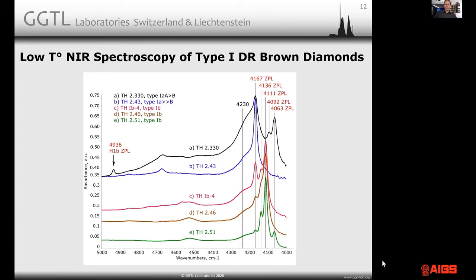So this is the low temperature work we've done on the Amber Center. You can see here on the left in the trace A, there is H1B zero phonon line. That might be surprising for many, that you find H1B in just a brown diamond. I assure you the diamond has not been treated. H1B is a very, very common defect in brown diamonds, particularly the ones that have the 4063 zero phonon of the Amber Center. So we found H1B and also H1C in such stones.